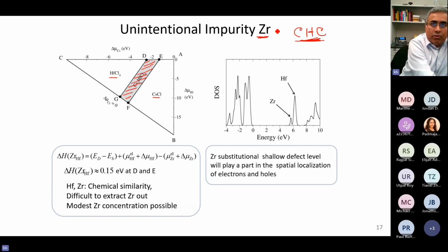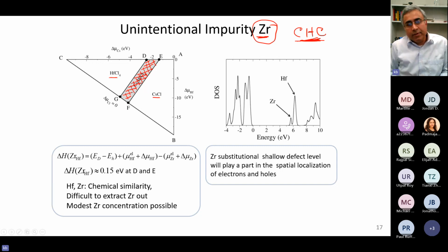When you are considering zirconium, you also need to include the compounds that zirconium can form, like zirconium chloride. So you have to take all of those competing phases into consideration, and then isolate the region in chemical potential space where cesium hafnium chloride will be stable against those competing phases. It is not easy to do, but if experimentally you can somehow confine to these chemical potential ranges, there is a very good chance that you will be able to grow pure cesium hafnium chloride. So that's the point of figuring this out.